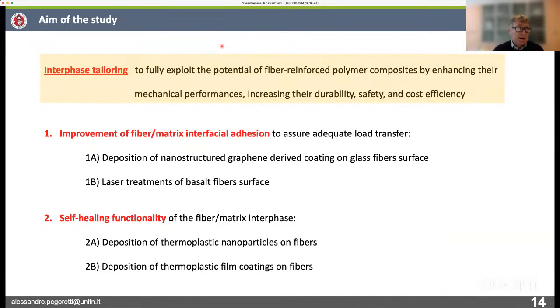So this brings me to the aim of this study, which is the interface tailoring. And in particular, we target two issues. One is, if it is possible, to improve the fiber matrix interfacial adhesion. And a couple of examples I would like to show you is how we can improve this by depositing nanostructured materials such as graphene, for example, on the glass fibers, or how can we modify the chemistry and the porosity and the roughness of the fibers by laser treatments. And this technique was applied on basalt fibers. And I will show you later the results that we can reach in this area.